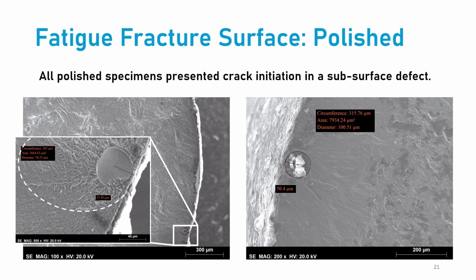Now, looking at the polished specimens, they all presented crack initiation at a subsurface defect. On the left, we have an average defect where we can observe the radius associated with the pore defect and the center distance towards the surface. On the right, we have specimen 6, which has an intersection with the free surface, which has led to a considerably lower life than predicted.